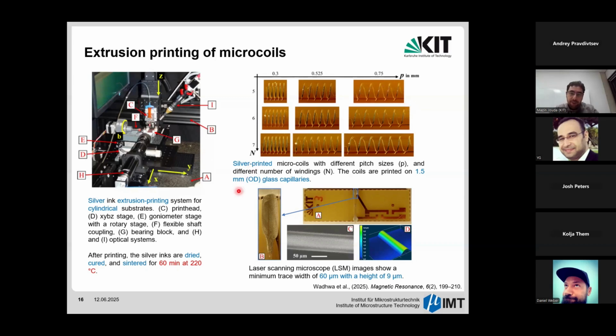After printing, we have to sinter the silver. So we put the printed microcoils in an oven at 220 degrees for 60 minutes for the sintering. From these laser scanning microscope images, you can see that we can achieve wire thicknesses down to 60 micrometers with a height of 9 micrometers. Of course, that can probably be pushed even further by optimizing the pressure, the printing parameters, and the speed by which we move the XY stage and the rotation.